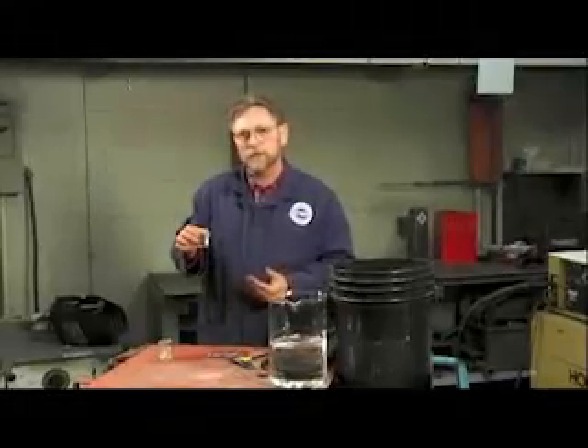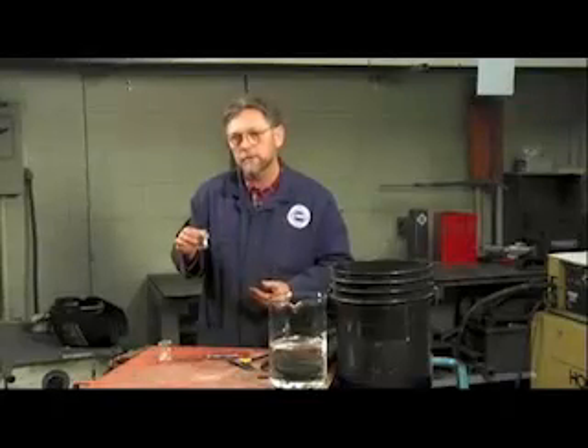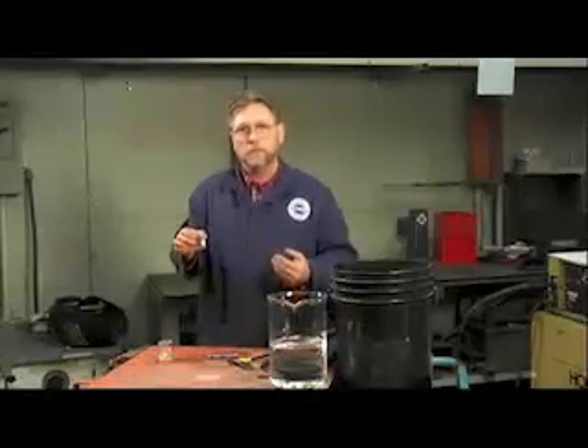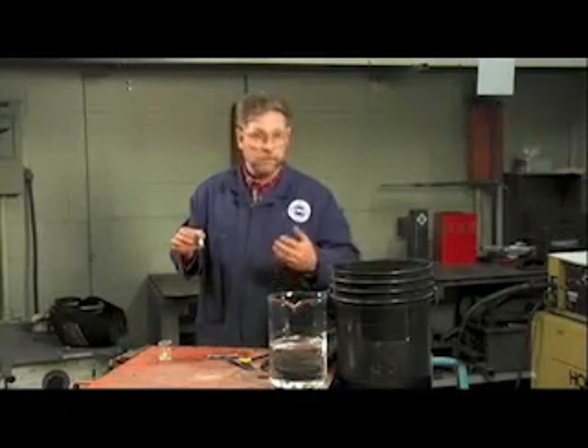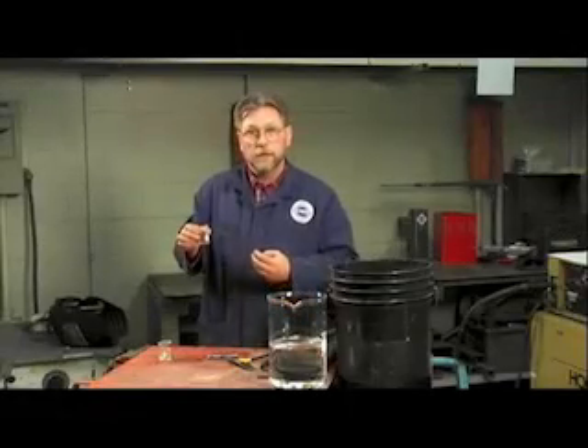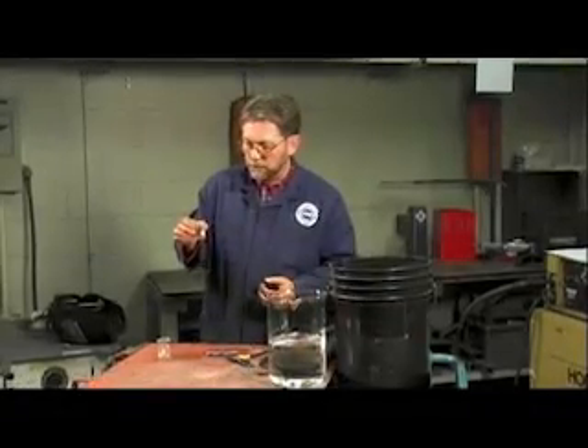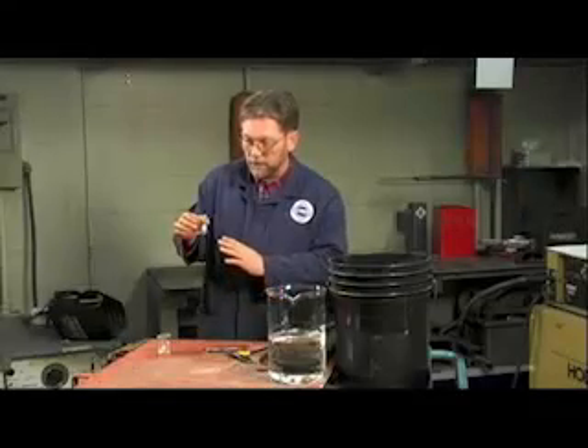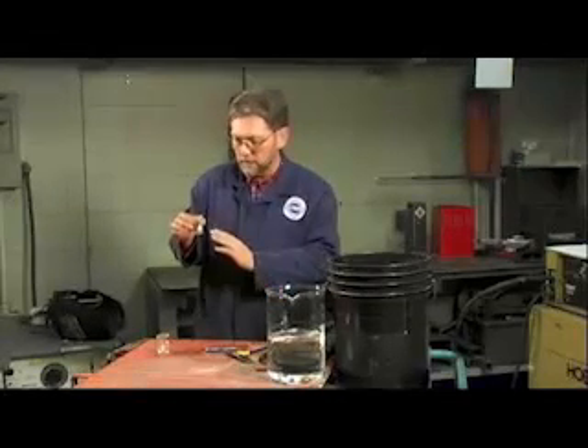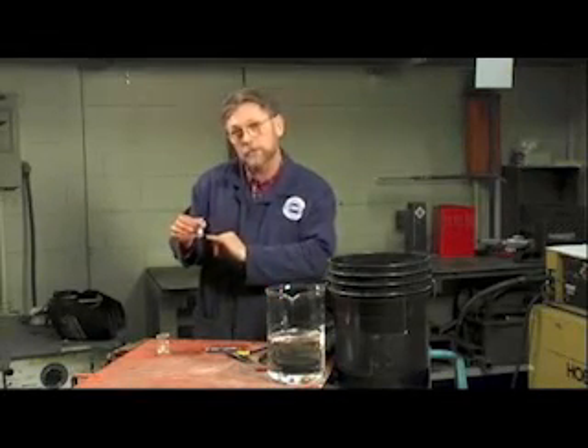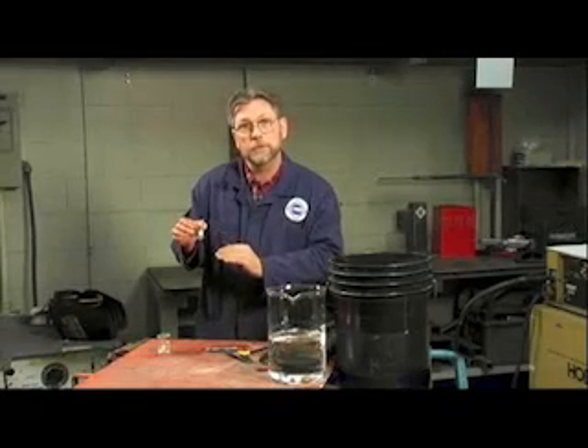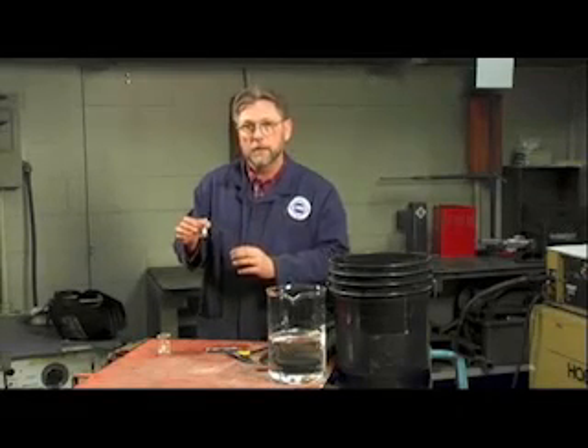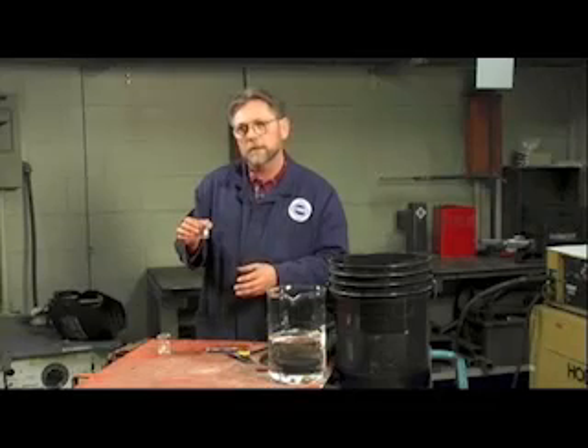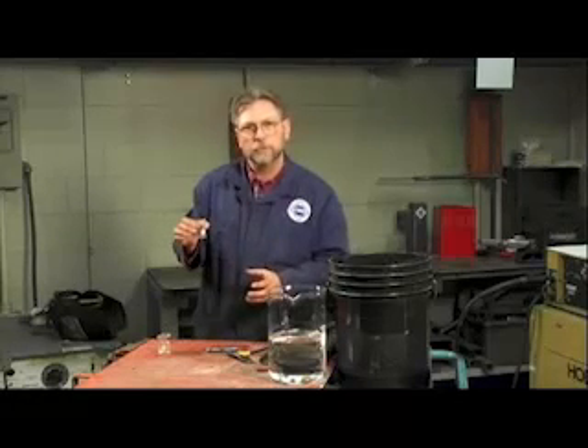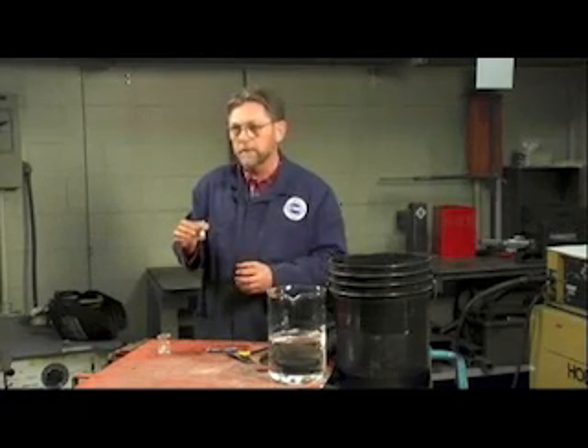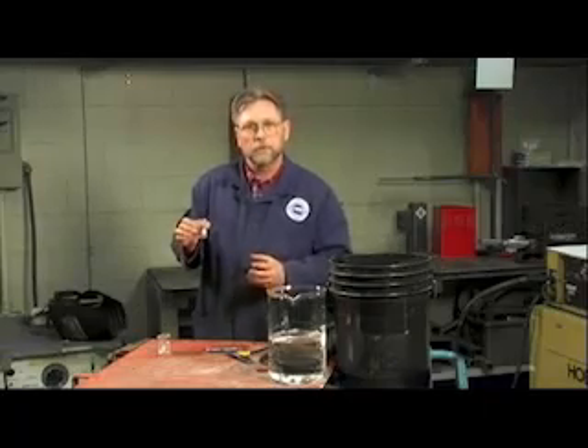Now, most codes and standards will set limits on the amount of hydrogen that can be absorbed by the metal based upon its service environment, the material type, and material strength. So in many cases we find that when we're trying to engineer a welding procedure that we need to define how much hydrogen we'll have as a maximum. 15 milliliters per 100 grams of deposited metal, 10 milliliters per 100 grams of deposited metal, 5 milliliters, and so forth, depending on the criticality and the strength of the material that's being used.